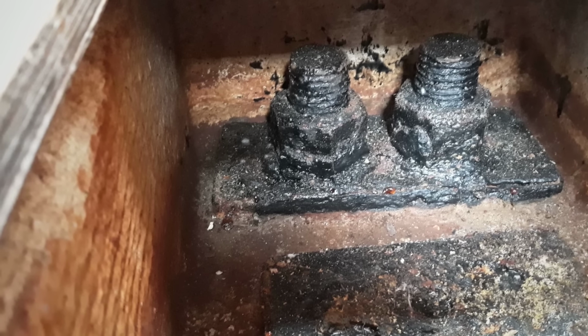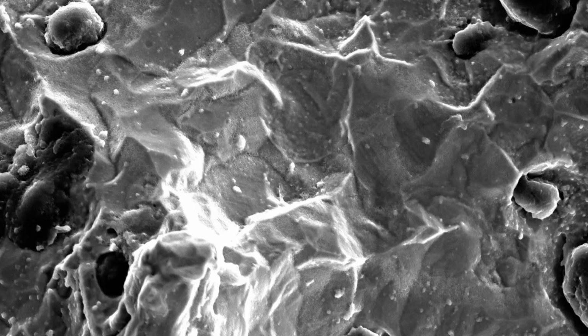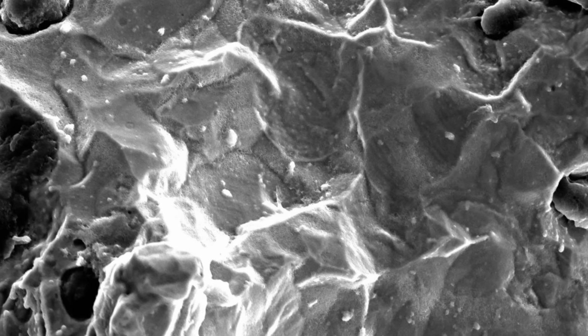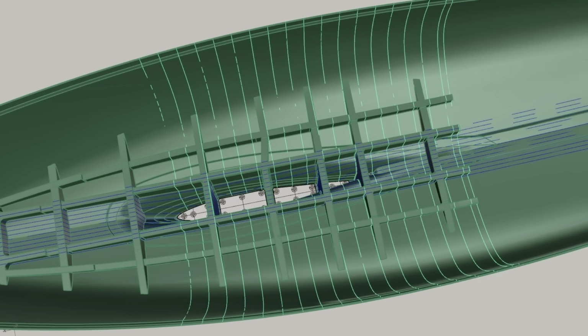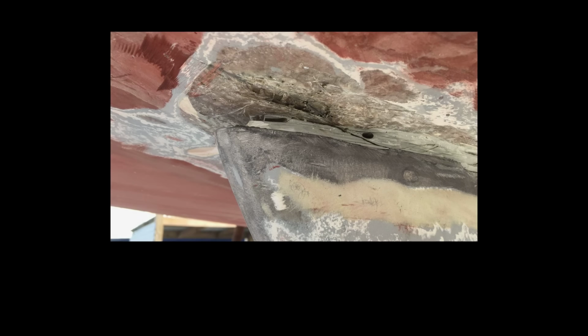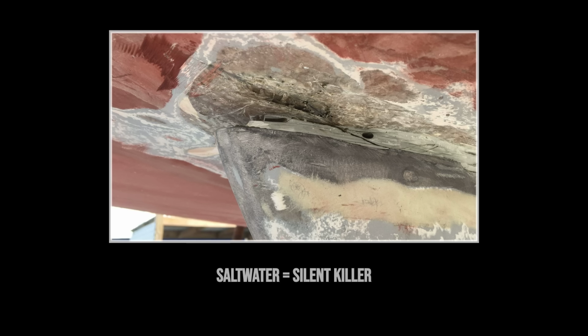In the yard, a foreman demonstrates with an old keel bolt, bending it gently until a faint crack appears. Under magnification, the fracture surface is dull and grainy, a classic sign of fatigue. In a real joint, this happens deep inside, often where water can creep in, accelerating damage through corrosion. The combination of bending, tension, and salt water is a recipe for disaster.